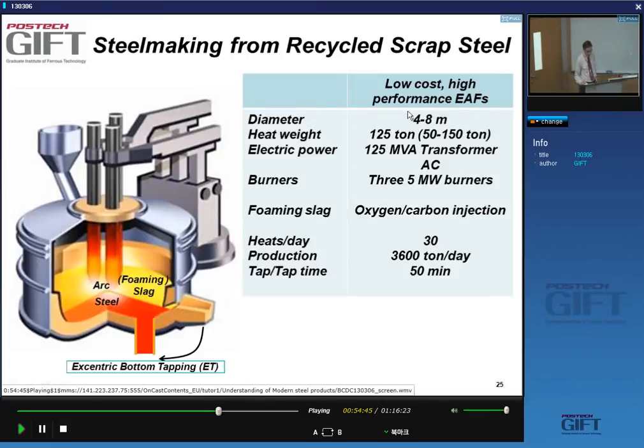The diameter of these things is 4 to 8 meters. The heat weights vary between 50 and 150 tons. The typical value is 125 tons. And of course, you need to have electric power installed. Usually we use alternating current electric arc furnaces. In addition, there are some burners to keep the metal warm on the top side, away from the electrodes. A typical electric arc furnace can do 30 heats per day, with a total production of about 3,600 tons per day. Tap-to-tap time is 50 minutes.